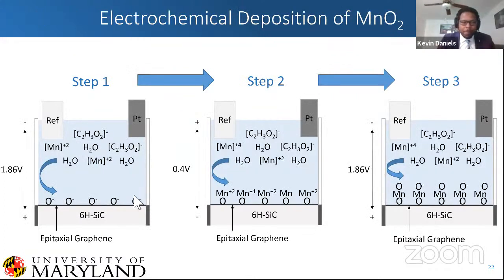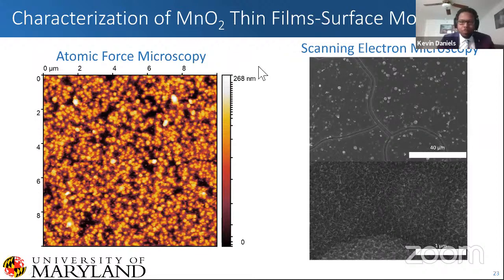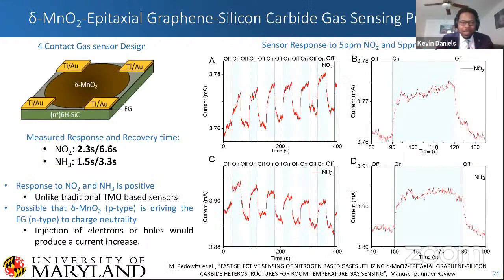So we decided to do it in 3 steps, where we seed the surface with oxygen here. Then we flip the potential and we put down our manganese, and then we flip the potential again. Then we cap it off with oxygen. And so the result of that is these thin films. Top surface is actually fibrous, which means that the material has even higher surface area than just a simple layered material would. And as a result, we made these 4 contact gas sensors on this electrodeposited manganese dioxide on epitaxial graphene. And we had a very surprising result, which was that we saw very, very fast response and recovery times. Response times of less than 3 seconds and recovery times of less than 7 seconds.